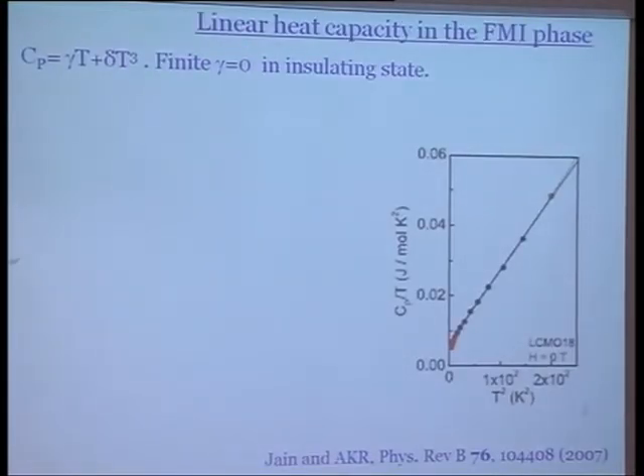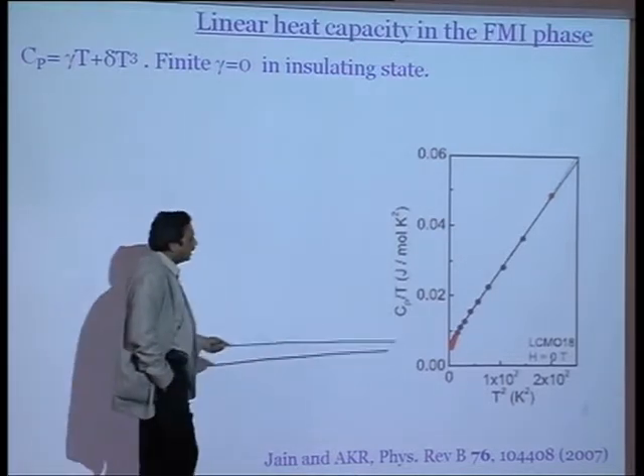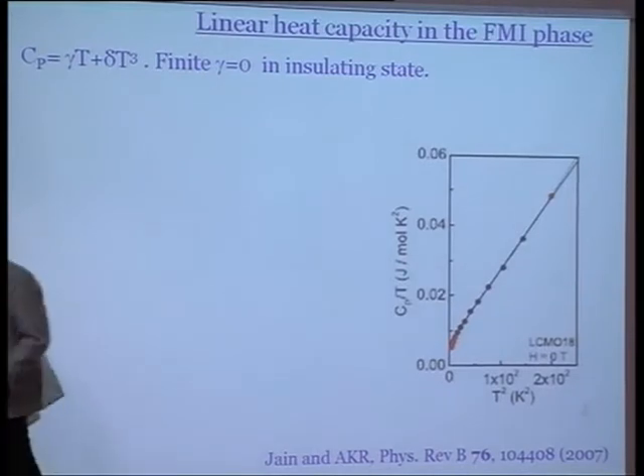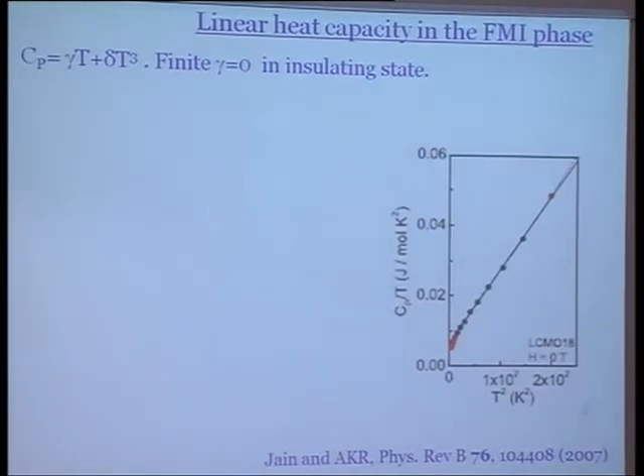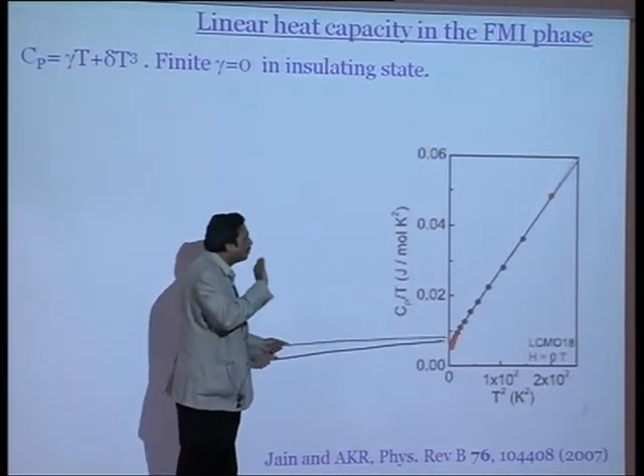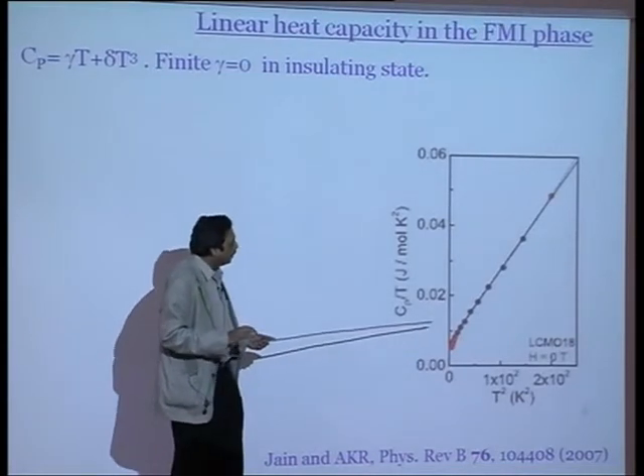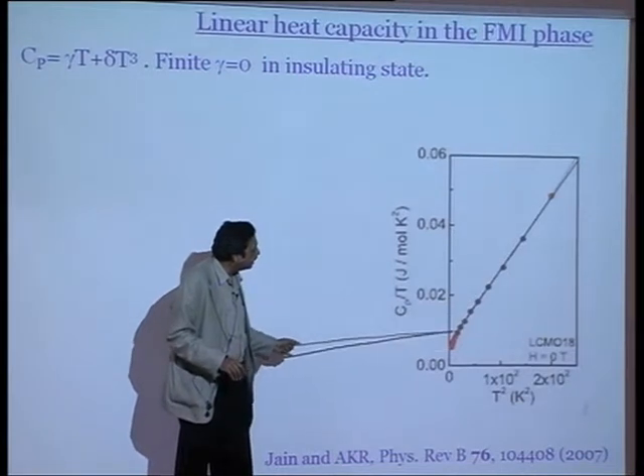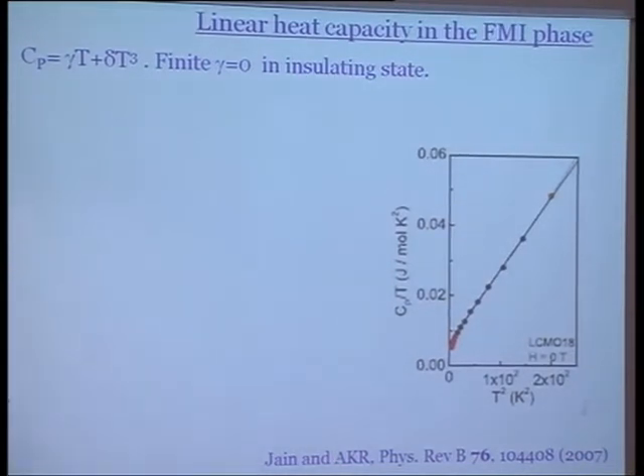Now let me come to the important point. This is an insulating state, and I would be expecting that the linear term in heat capacity should vanish, but if you measure the heat capacity, you find it doesn't vanish. There is a little small term over there, and this is the term which is telling you that you are dealing with a kind of insulator which is not a truly band insulator. And this extra linear term that you're getting over here is not coming from any magnetic origin. For if we apply something like 14 Tesla, the black and the red curves fall on each other. The black curve is at 0 Tesla and the red curve is at 14 Tesla, and these two fall on each other, so there is no magnetic component present over there.